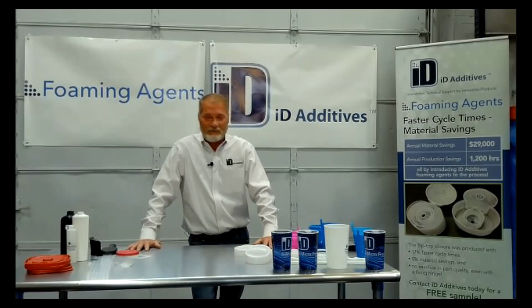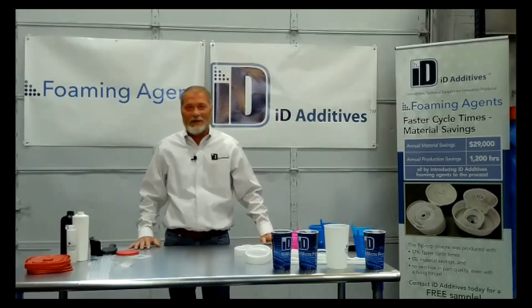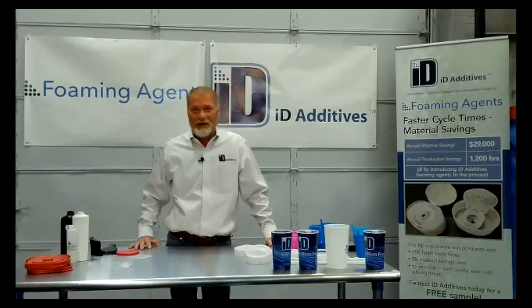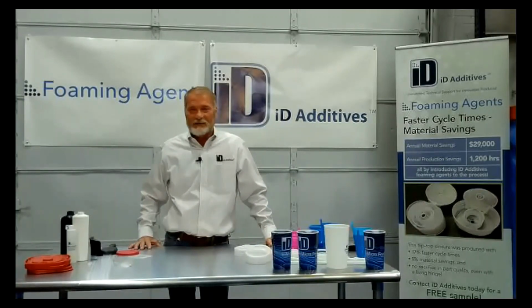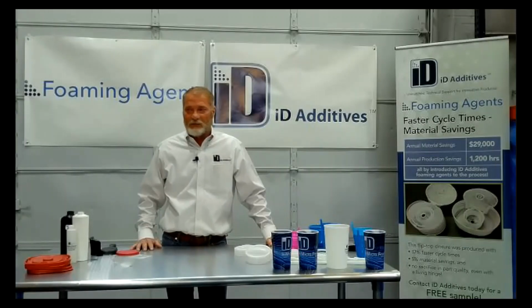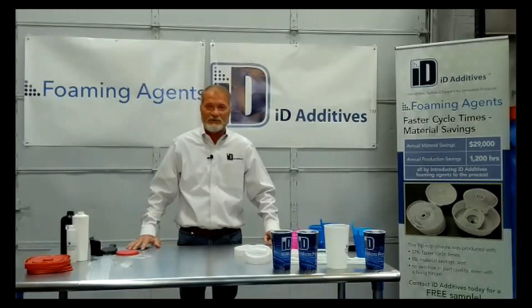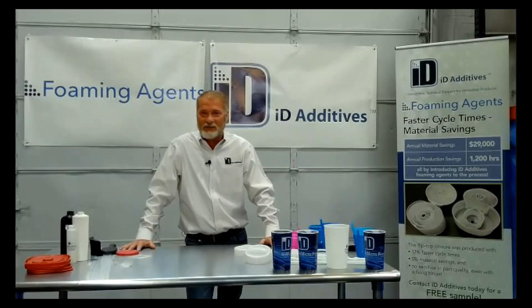We've done a lot of cups, and they foam really well. I don't know why they don't want to do it. They foam really nice, but if you have an imbalance, then you're not going to get the same shot weight or part weight in each one, and things are going to change. But as far as filling with low pressure, balancing, making sure that you take advantage of that viscosity change, dropping temperatures, keeping the residence time down, you can get some great cell structure in cups.